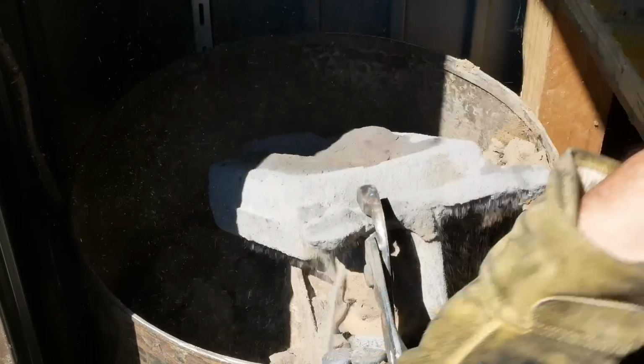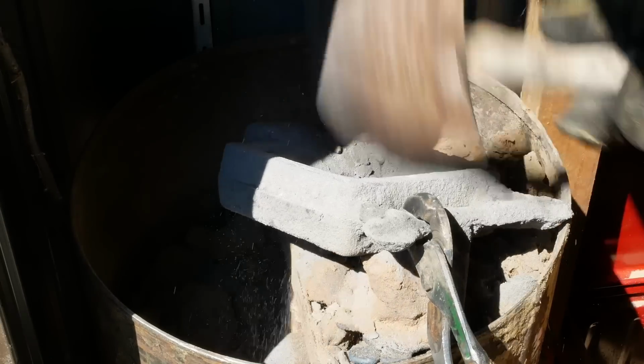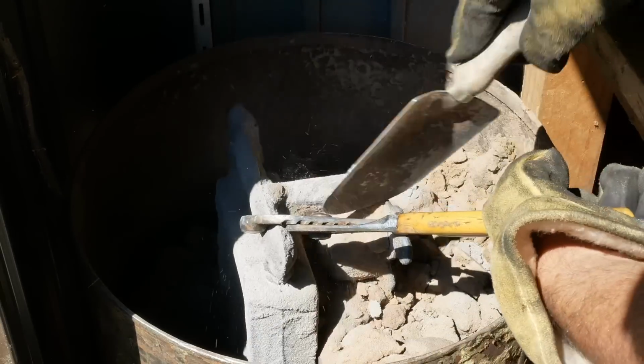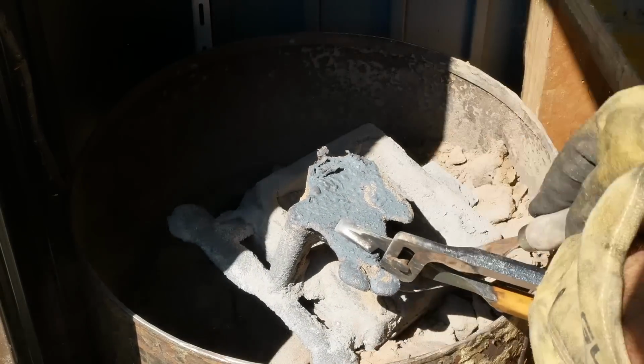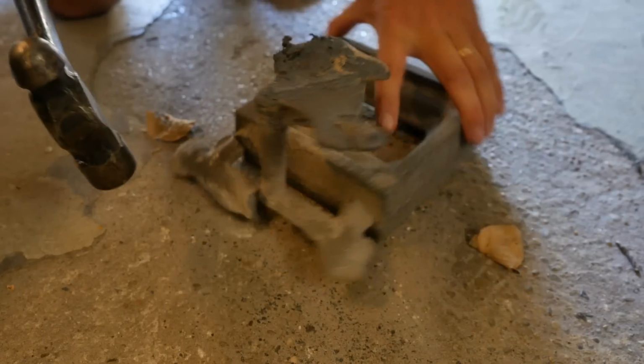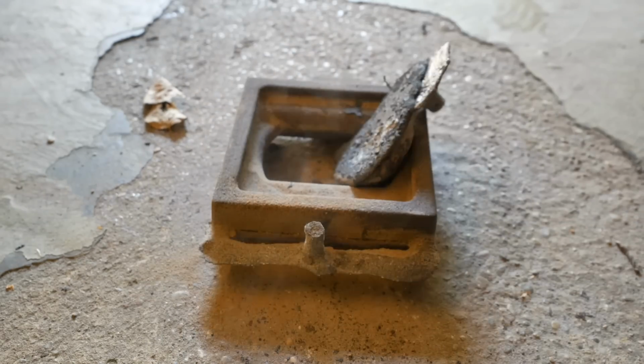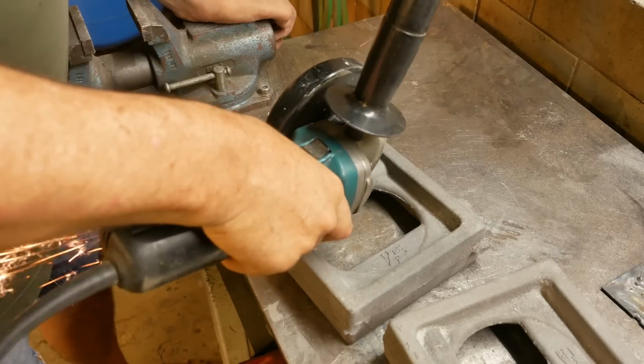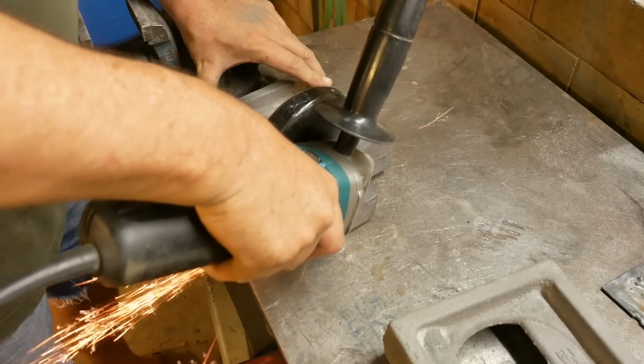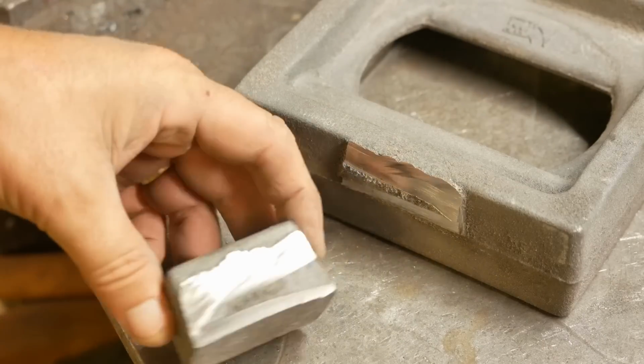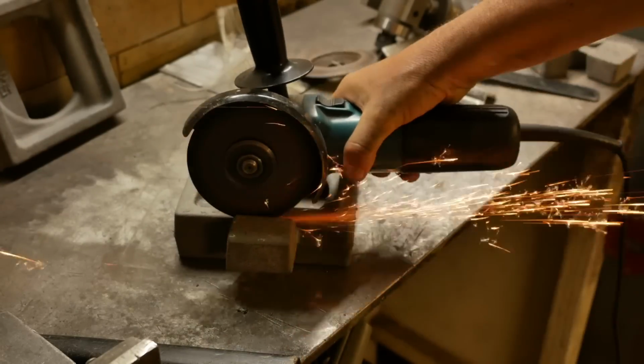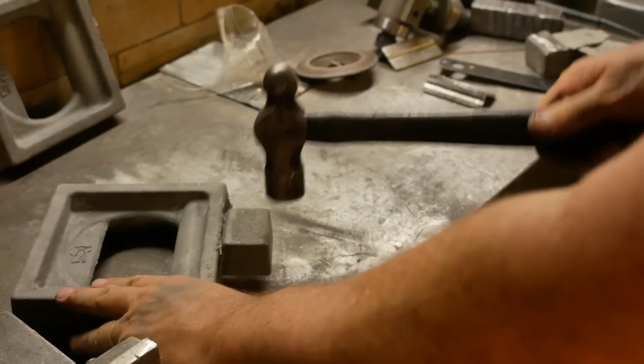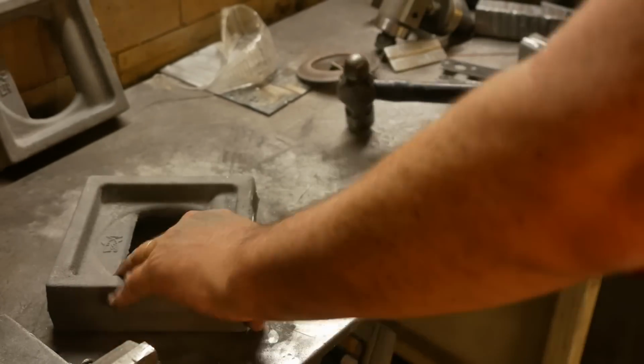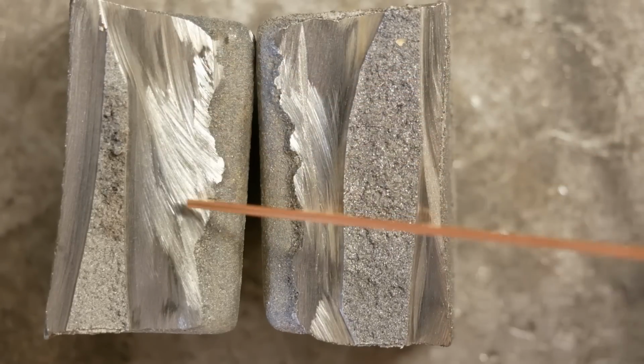If I had a mould wash of graphite and put that on the surface of the sand before I closed the mould, I wouldn't have quite as much sand sticking here and would have got a better surface finish. Here you can see where I ended up putting that shrink bob. Well, the iron where I cut looks lovely, nice and solid, no inclusions. I hope it's the same on the other side.